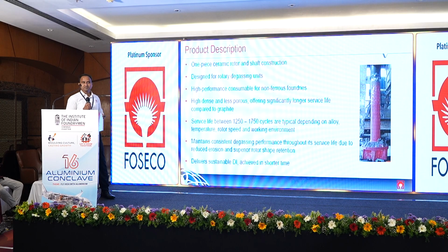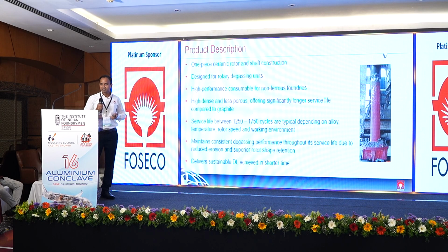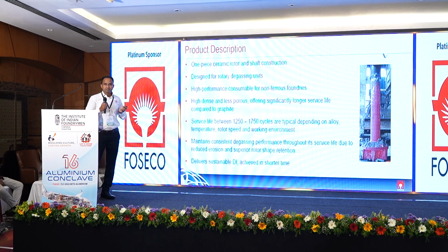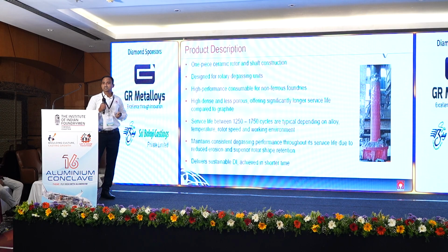Once we do degassing, immediately after degassing we achieve a density of 2.64 gram per cc. But after some time, 10 minutes or 15 minutes, it increases because of hydrogen and oxygen pickup from the atmosphere, and the density index increases by 3%, 4%. But because of the geometry of this rotor, as well as its high dense and low porosity properties, it sustains this density throughout 1 hour to 1.5 hours.